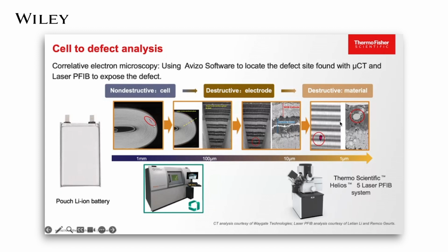You can move from CT to DualBeam by using sample holders that allow us to lock onto different features at macro scale and then turn those into micro scale, so that you go straight to the site-specific locations and make the cross-section with high throughput tri beam tools or DualBeam tools, or do SEM EDS analysis to understand the mechanism of the failure.